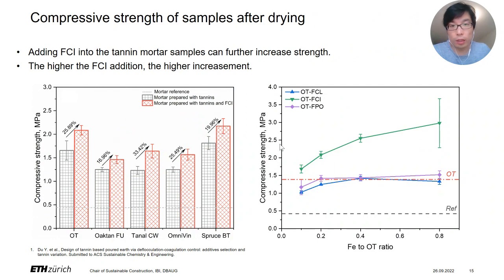And we also measured the compressive strength of the sample after drying. Except for adding the phosphate one, by adding iron chloride, we can not only remove the dispersing effect, we can also further increase the strength. And the higher the addition, the higher the increase.